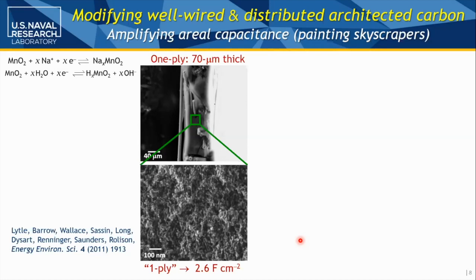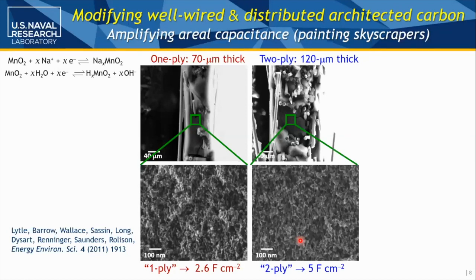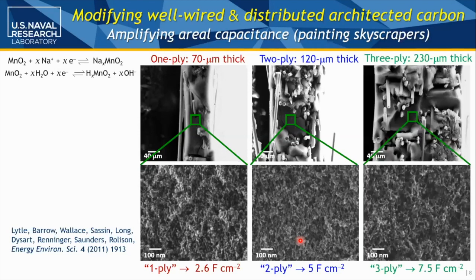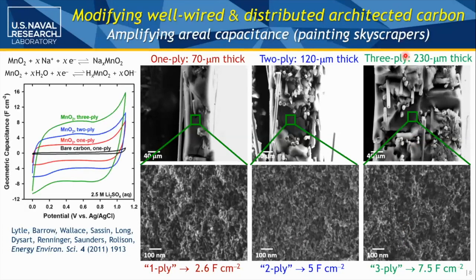And so she did the voltammetry on that, current voltage curve, nice envelope, and normalized to 2.6 farads of stored energy per square centimeter. 2-ply cross-section, you can see the good fill factor doubled, went to 5. 3-ply, we're now 3 times that. And that told us we had good connectivity of that void across a large macroscale distance. You can see the 3-ply here is over 200 microns thick. And from your pattern recognition, you can see how boring just the plain carbon nanofoam paper is at a 1-ply. And then we've painted it with manganese oxide, 2-ply, 3-ply.